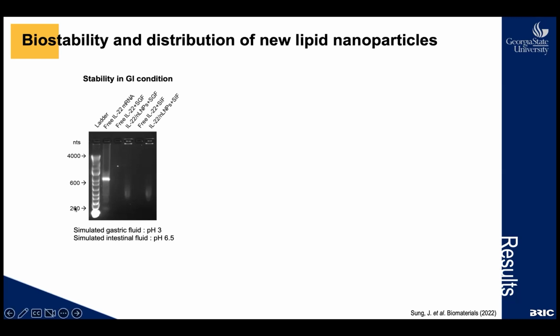The very first left sample is free IL-22 mRNA without the exposure to acidic fluids, and the next 4 samples were incubated in the fluids for 4 hours. As we can see here, the free IL-22 mRNAs were all gone, and the encapsulated IL-22 mRNAs were mostly protected, but some of them were destroyed by the acidic conditions.